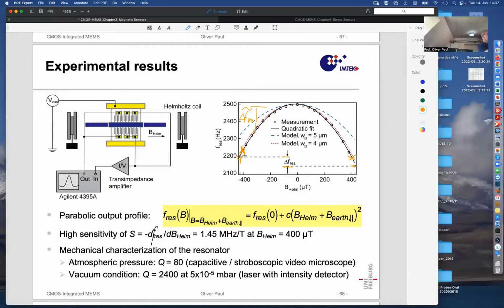20, 25 or so micro Tesla is small, but it produces an effect here. And then, well, also, of course, this device was characterized in vacuum as well as atmospheric pressure, and it resonates much better, with a much sharper resonance frequency in vacuum than in air, where it is broadly damped by frictional effects in air, by squeeze film damping, present in mechanically moving microstructures in air. So under vacuum, the sensor has a chance to enable better resolution of the change of the resonance frequency by the magnetic field, and therefore also better resolution of this delta F.